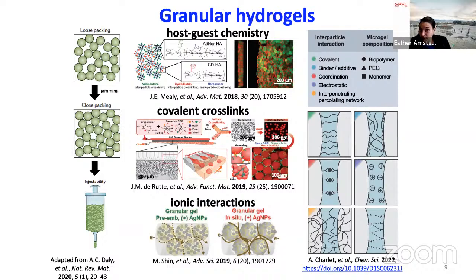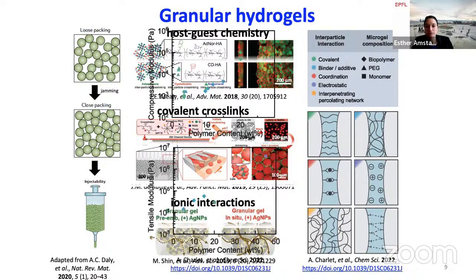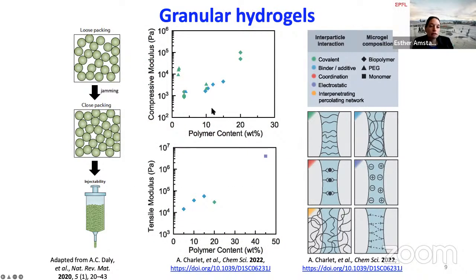Now, once I started thinking about it, one of the possible reasons for this weakness is that these particles are spherical, so their contact area is very small, and that means that the density of the interparticle connections is also very low. I think this is the reason for the softness of these materials. If you just have very few bonds, even if the bonds are strong themselves, like covalent bonds, you still get a weak material overall because of the low cross-linking density. So again, if you look at the stiffness as well as the toughness, you're in a similar range as the range I showed you before, 10 to 100 kilopascal Young's modulus.